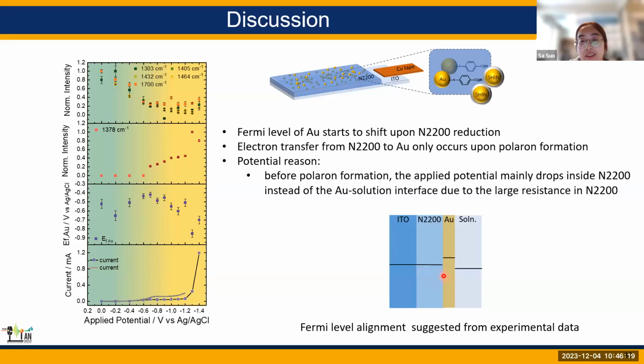we can see that the N2200 Fermi level first changes, but the gold Fermi level wouldn't change. But after some point, the gold Fermi level will change with N2200 once it can get electron transfer from N2200 to gold. I think this is the main conclusion that we have right now, and we have more to explore.